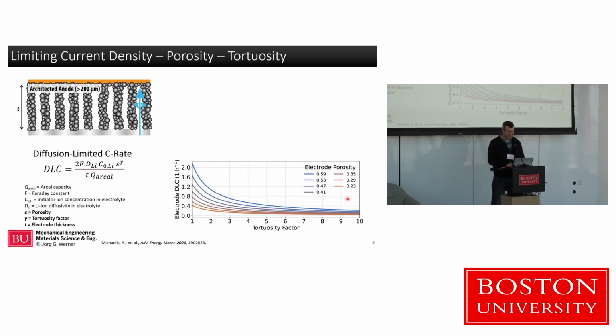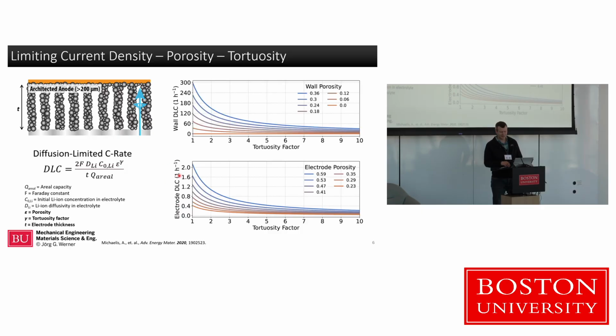So over 200 microns, you can see here that even at a moderate tortuosity, you're limited often to C rates, meaning how fast you can charge it, to 1, meaning an hour or slower, right? But you can also see that by changing your tortuosity, let's say for 1 porosity, you can actually double or almost triple that C rate, going from a tortuosity of 6 to a tortuosity of 1 or so. So tortuosity is really something that seems important, especially if we're thinking about, well, how fast do we really need to charge our battery? 5 minutes might be fast enough, right? That would be C rate of 12. So that would be a good target. But here we're not even getting beyond 2 when we make such thick electrodes.